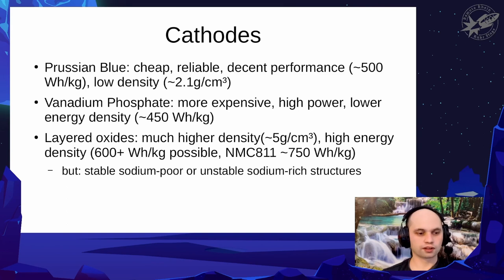And then there are layered oxides. Layered oxides are the same kinds of materials that you would have in most lithium-ion batteries. What is usually used here is manganese. It's not so much nickel-based. You can use nickel, and sometimes nickel is used to improve the energy density, but there have been very good results with almost pure manganese oxide with just some stabilizing other materials, and you can get 600 watt hours per kilogram, and some of the best lithium materials only reach about 750. So it's about 80% of what you would get with lithium. But there are some other problems.